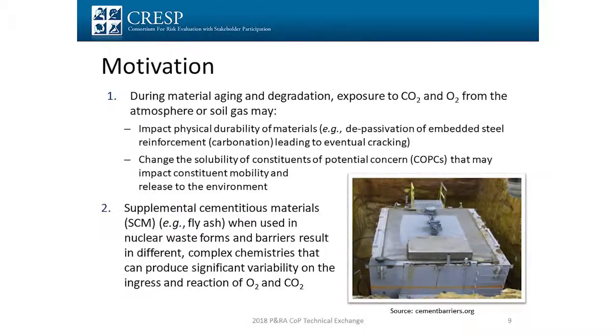So I'm going to get into some of the experimental work and some of the motivation of this. We've looked at a lot of effects of carbonation and oxidation on both vault concretes and high salt waste materials. This is because these sorts of things can affect not only the microstructure of the material, but the redox state and therefore some of the solubilities of key constituents. So we've been looking at that. And then the effect of, when I was looking at the tank closure scenario for a 65-year-old Hanford tank, I didn't really have to worry much about supplemental cementitious materials. But when you look at, say, vault concretes at Savannah River or IDF at Hanford, you're going to have to start worrying about supplemental materials. So what are the impacts of these on the alkalinity and some of the other effects that you're going to see?